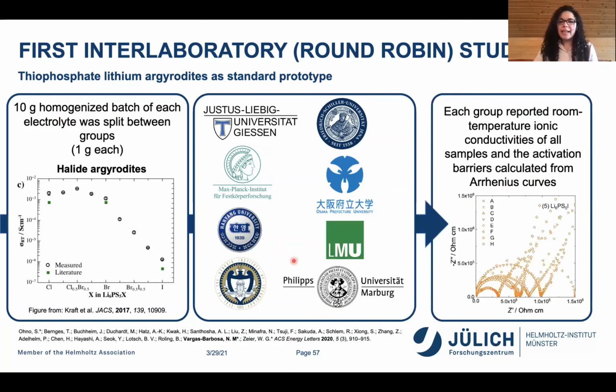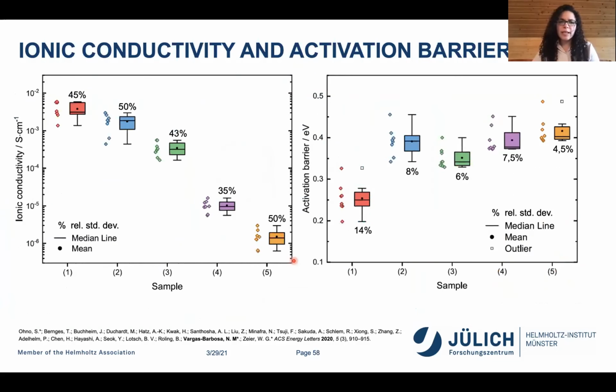And then we simply had them report room temperature conductivities of all of the samples, as well as the activation barriers that they calculated from their Arrhenius curves. And this is what we obtain, which is crazy in some ways. So here are the 5 different samples in a box plot representation. The line represents the median, and the dot in the middle of the box represents the average, the mean. And the percentages here are the relative standard deviations of the data.